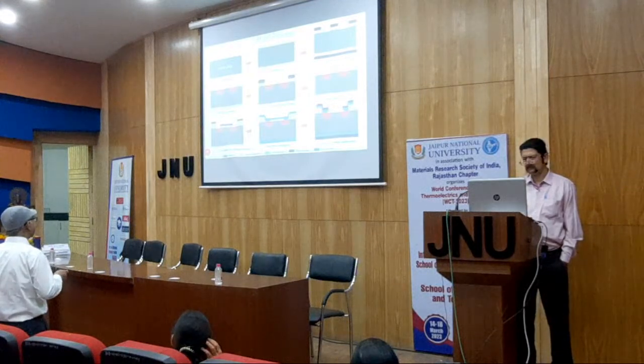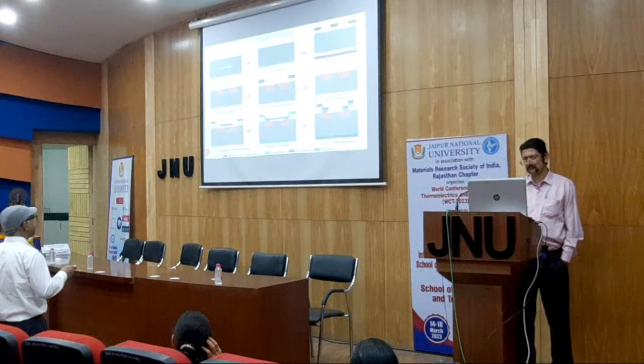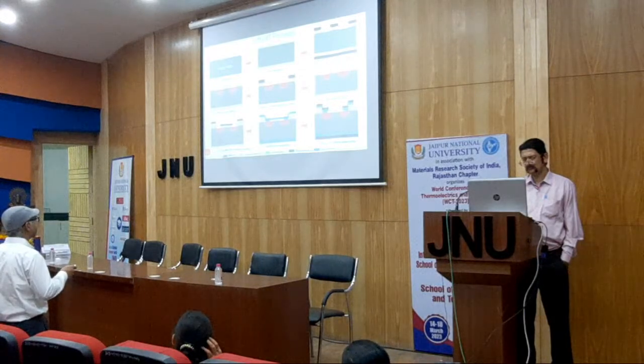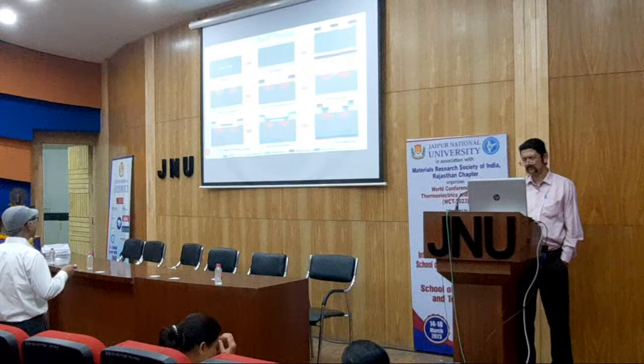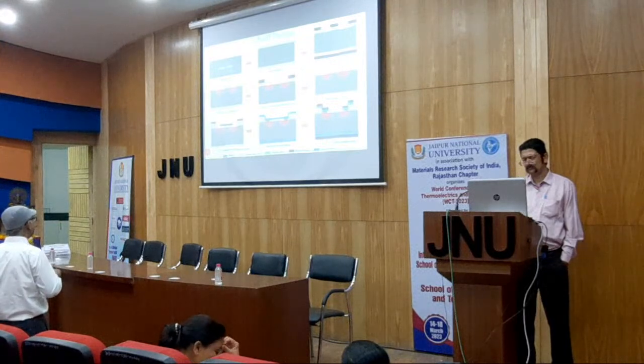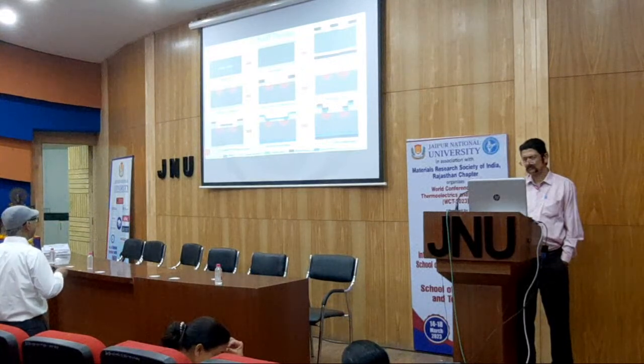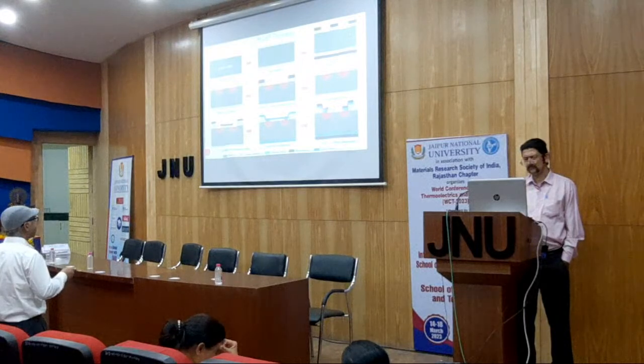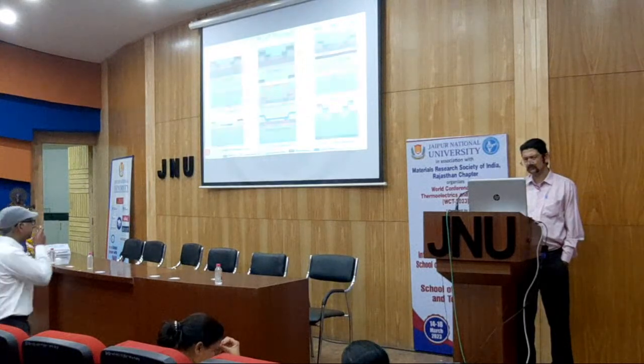Then oxide and PSG, meaning phosphorus doped glass, is deposited and then removed, and the gate oxide also has been removed. Now we did the blanket deposition of oxide, which is a high quality, high density oxide that will work as a gate oxide. Then they did the lithography, the source drain contacts were opened, and metallization was performed. After the lithography, metal was deposited and patterned. Next, please.